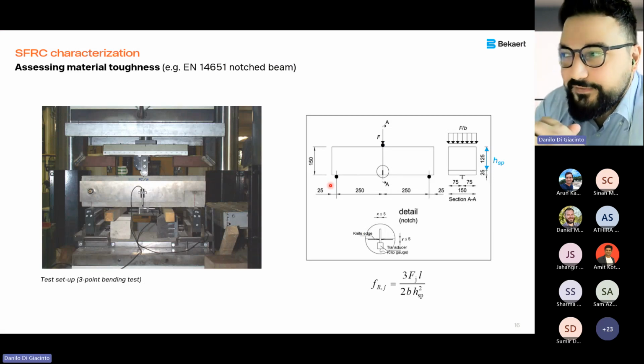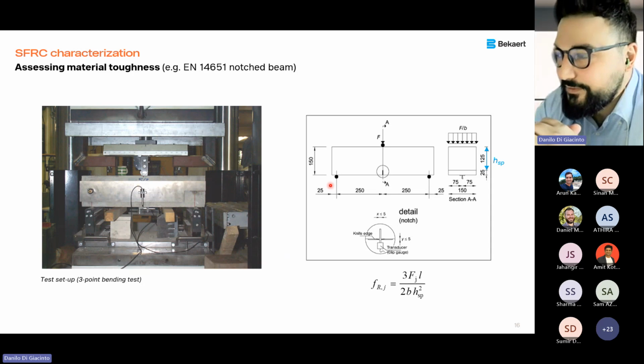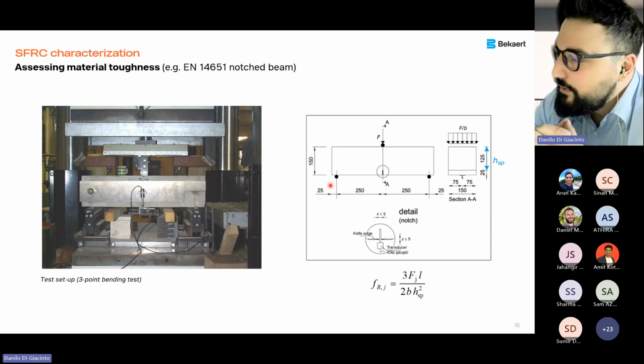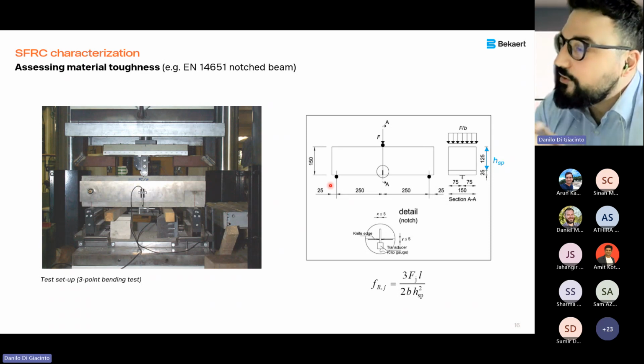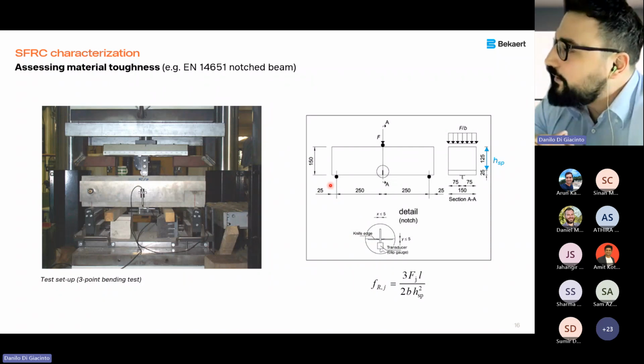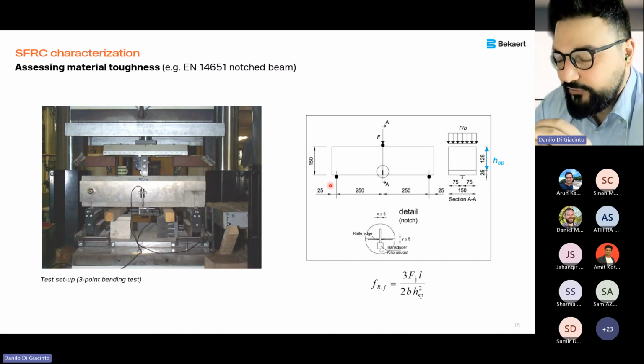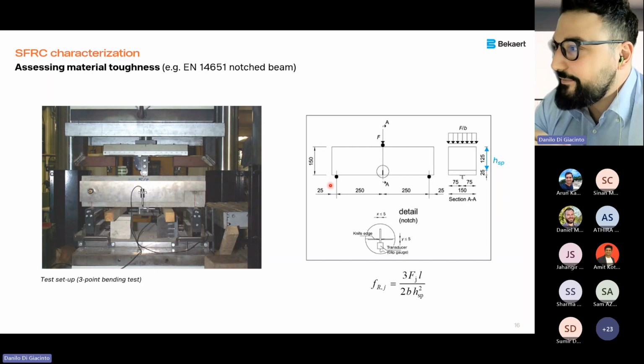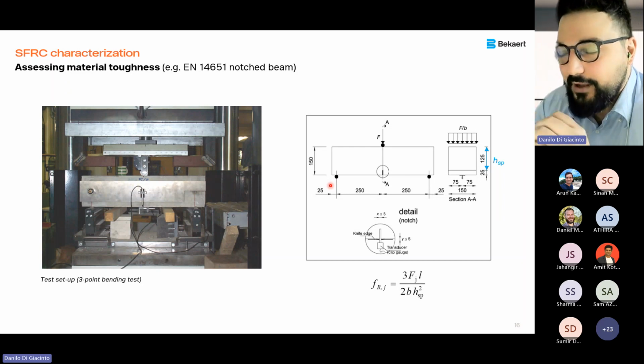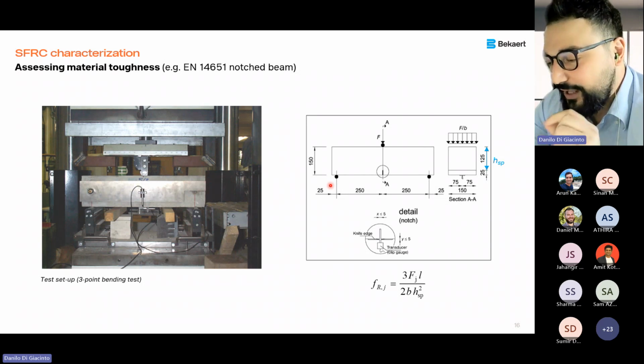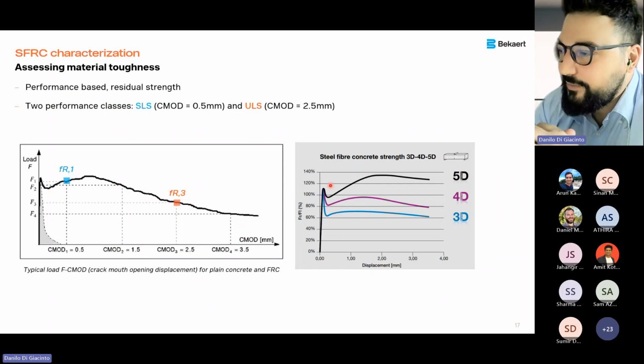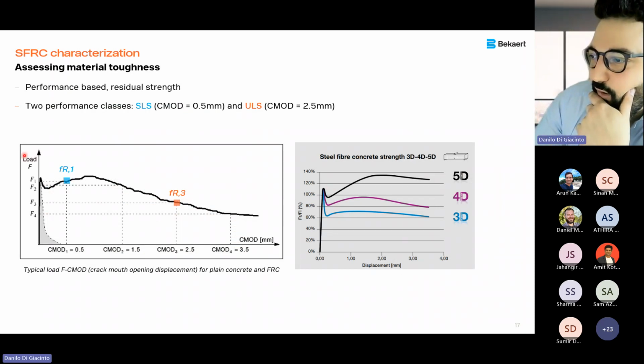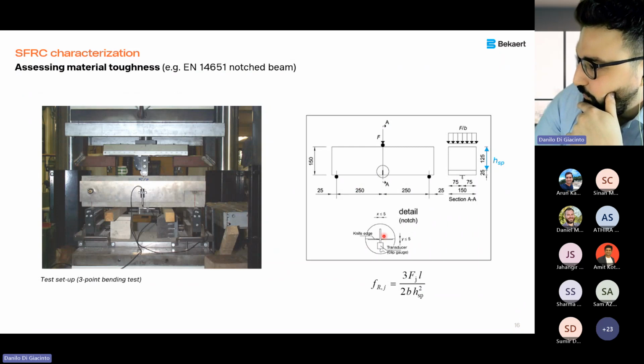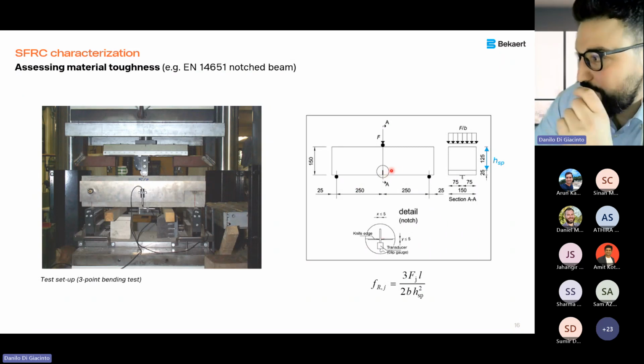How do you characterize your SFRC performance, so the toughness of the material? There are several standardized tests. For example, this is a very important test which is used worldwide, but is a European standard. You do a 3-point flexural bending test on a standardized beam with an initiated cracking path. So you have the notch in the middle of the beam in which the crack is initiated. What do you get? You get some curves. These are typical curves with the load on the y-axis and the CMOD on the x-axis. CMOD is the crack mouth opening displacement, so basically the distance between the two faces of the initiated crack at the notch.